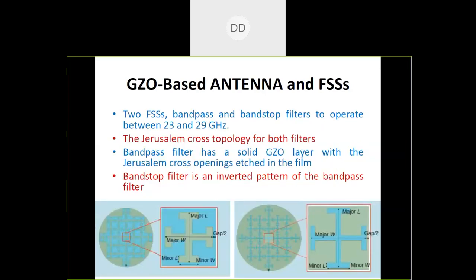These diagrams show the two frequency selective surfaces designed on the said substrate using the gallium doped zinc oxide layer. This side is designed for the band pass operation, and this side is designed for the band stop operation. A band pass filter and a band stop filter working between 23 to 29 gigahertz have been designed, and they used the Jerusalem cross topology for both filters.